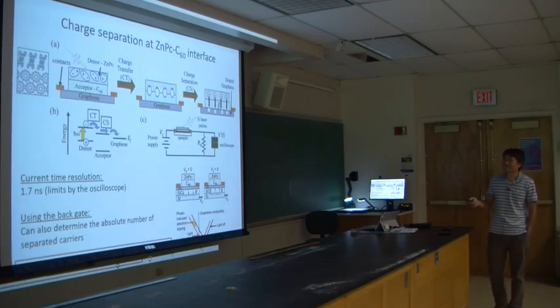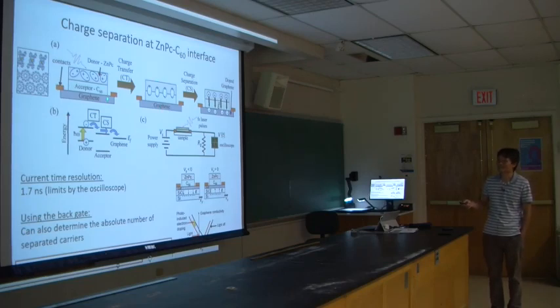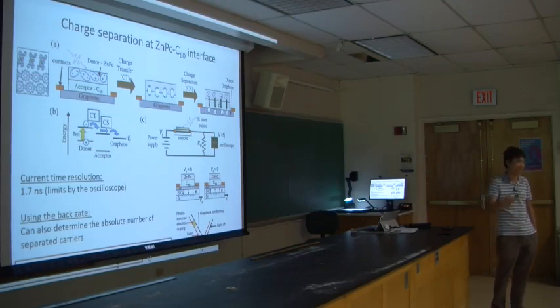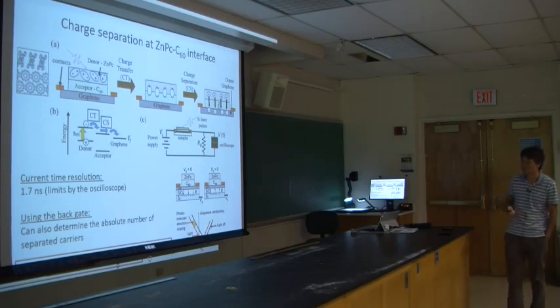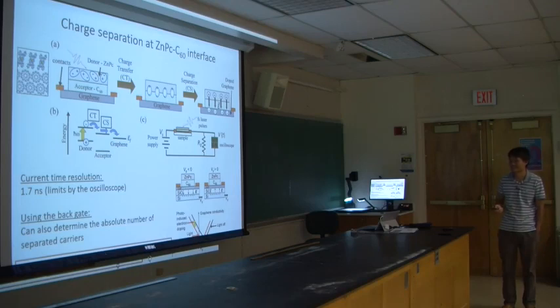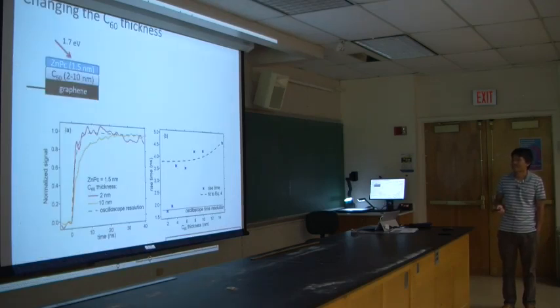We grow the same type of sample, a donor-acceptor interface, but on graphene instead of the gold substrate. Then we measure the number of carriers transferred into the graphene, generated by this charge separation. So here are some of the dynamics we obtained.